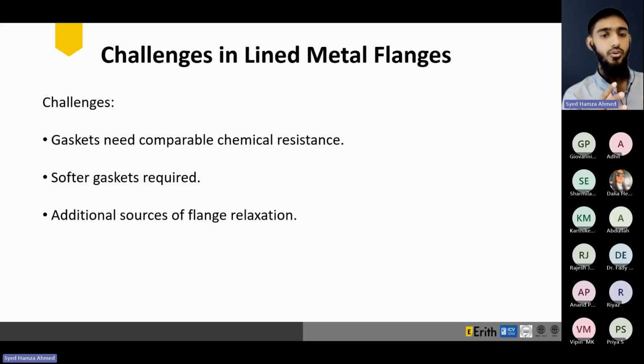As these flanges typically have low allowable torques, we have to keep in mind, once assembled, the connection now has two sources of relaxation because of the liners on each flange along with the gasket. They are in compression. So again, we have the liner as well as the gasket. These two have to be considered when taking into account the allowable torque, as well as the relaxations that are going to be there in the flange connection. So it goes without saying that retorquing before starting up is highly recommended, since they have additional sources of flange relaxation.